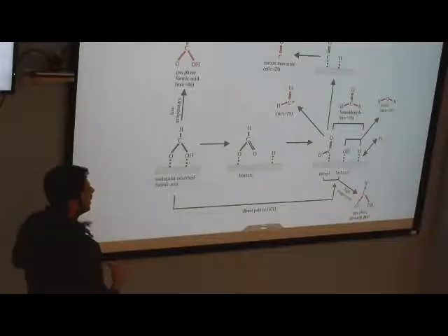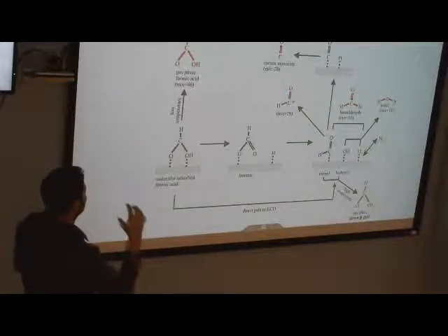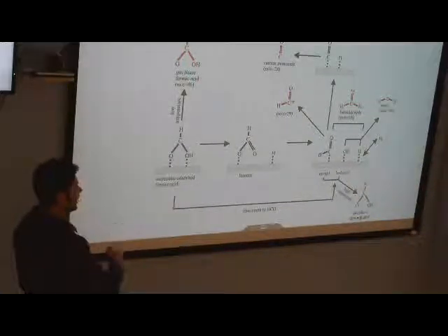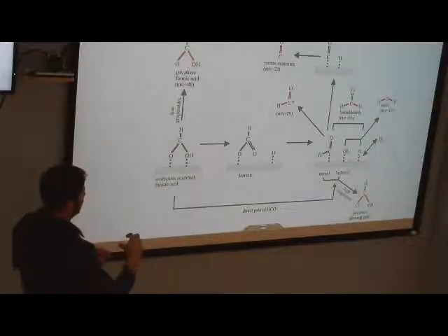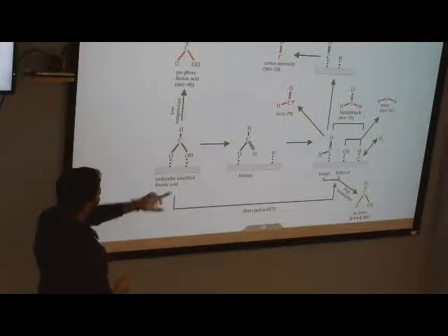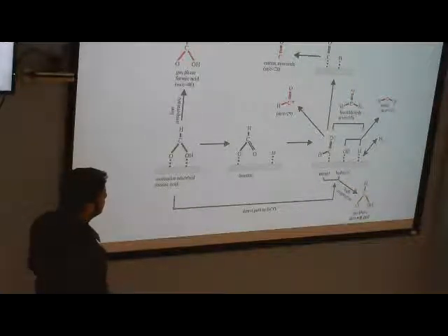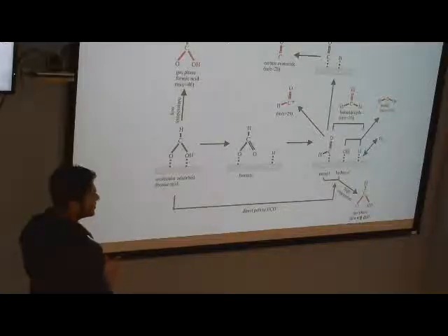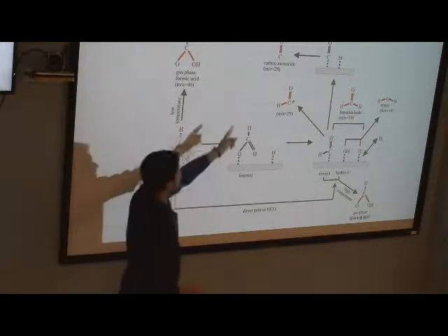Depending on the reactivity of those binding sites, formic acid can bind itself, or it can dissociate with the impact and form formate and adsorbed hydrogen, or it can dissociate further to form those kinds of fragments. We couldn't characterize those fragments exactly. We need some kind of IR spectroscopy or another technique to characterize those things. We could only detect these fragments.